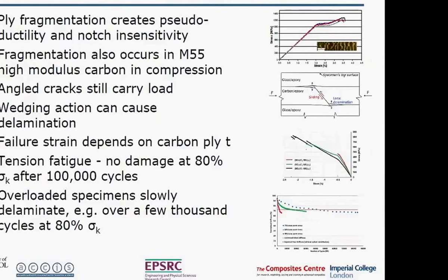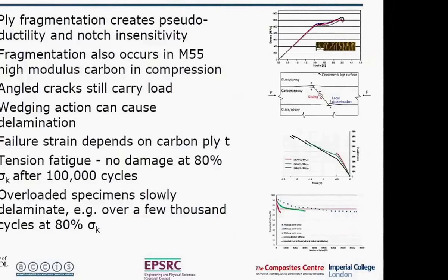Okay, so in conclusion, what I've shown here is that the ply fragmentation causes pseudo-ductility, and as a result of that, we get a notch insensitivity response, which is really encouraging, that we want to see. What we've also found is that this fragmentation mechanism also occurs in M55 high modulus carbon in compression. I haven't talked about what happens in other carbon fibers. We've also done this looking at high strength carbon fibers, and that could be another presentation. It's also very interesting because we have very high strains on standard modulus carbon fibers, and they don't fail. We measured this as high as 3.5% in a standard carbon fiber in this situation, which is extraordinarily high, and that's a whole other story.